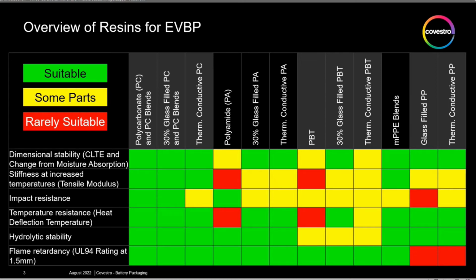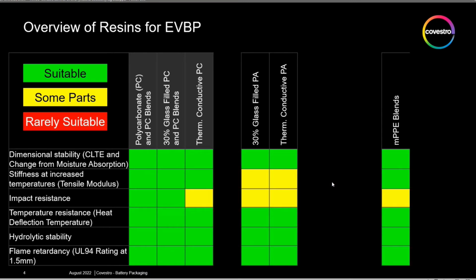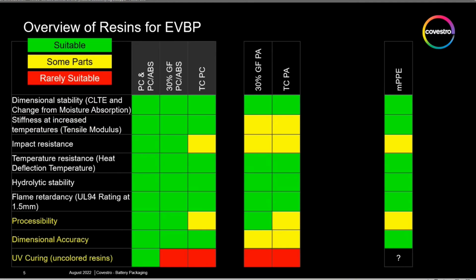We often need good impact resistance, obviously, so the battery doesn't get damaged. Temperature resistance to heat, hydrolytic stability, so when it comes in contact with water, it doesn't deform. And of course, we often want to see flame retardancy based on a UL94 rating of V0 at 1.5 millimeters. So as you can see in this chart, we identify where some of these materials either pass or fail these criteria. If we eliminate some of the ones that don't do very well, we're really left with about 6 materials left to choose from for EV battery packs.